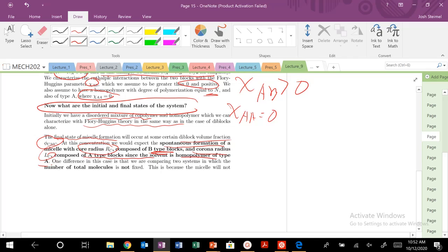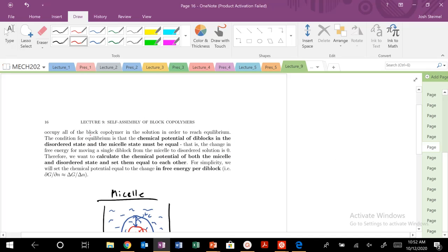So the one thing that we need to think about is that in these two systems, the total number of molecules is not fixed. This is because the micelle is not going to occupy all of the block copolymer in the solution in order to reach equilibrium. There's going to be multiple micelles happening here. So once you've hit that critical micelle concentration, it's not just one micelle with everything. At the critical micelle concentration, you start to self-assemble and form micelles. But anyways, the key condition for equilibrium is that our chemical potential of diblocks in the disordered and micelle state